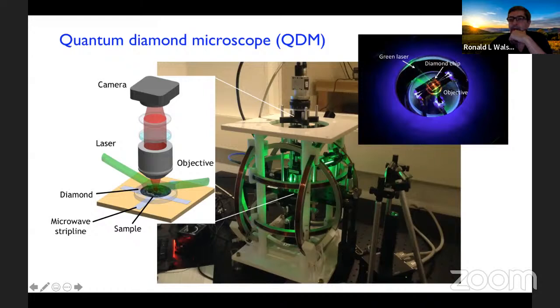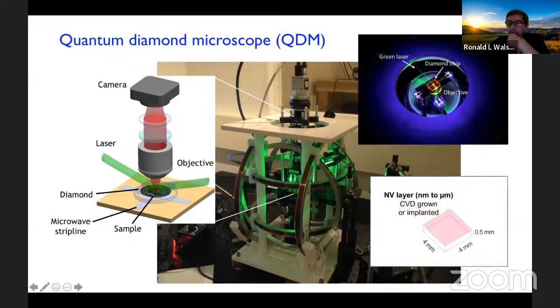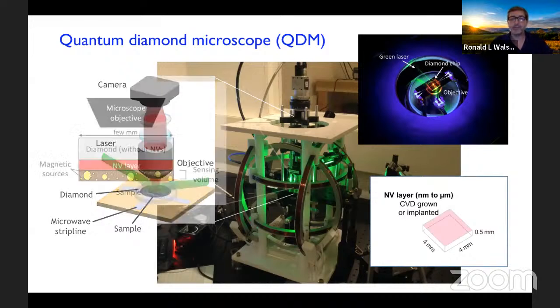There's the microscope objective. Here's the diamond. You can see the green laser coming from the side. The surface of the diamond that has lots of NVs in it is glowing red. You can see a lot of the other components. The sample has been removed here. These diamonds usually are something like this, a few millimeters on the side, about 0.5 millimeter or so in thickness, and with the NVs only at the surface layer. There's a dense NV layer, but only at the surface. Now, how thick on the surface? It could be a few nanometers to tens of microns, depending upon what you want for your certain application.